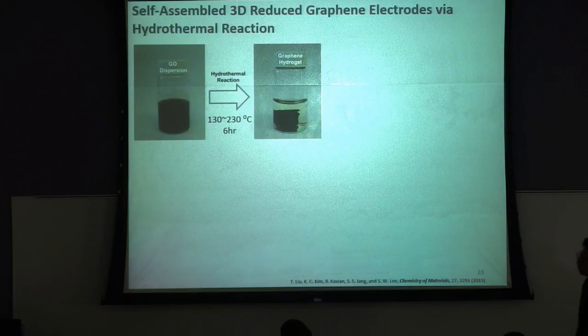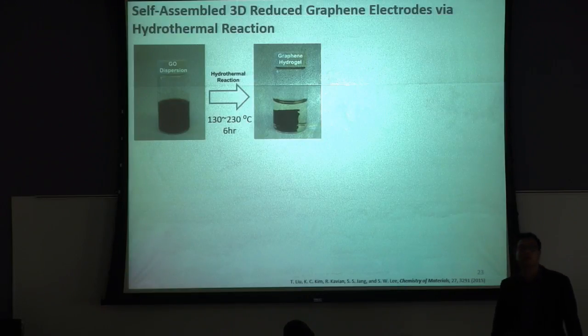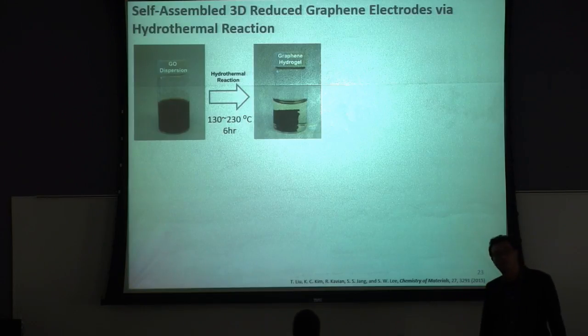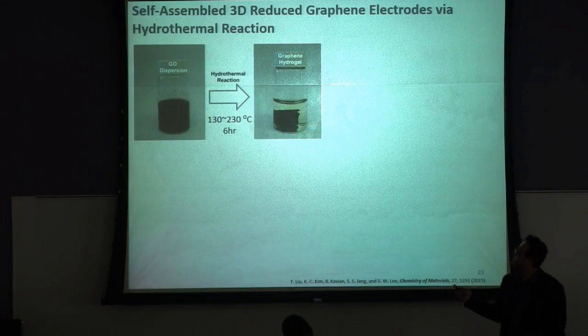Then this proton can reduce this graphene oxide. The reduced graphene oxide can recover its sp2 conjugation network, right? Then the reduced graphene oxide has van der Waals and pi-pi interactions, so they self-assemble, generating this kind of graphene hydrogel.